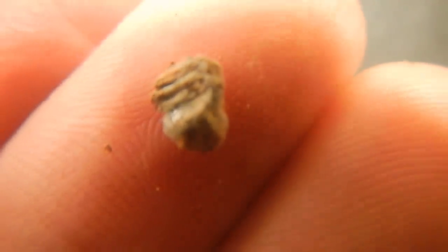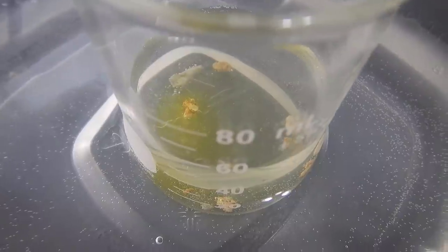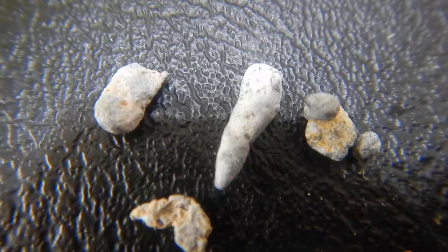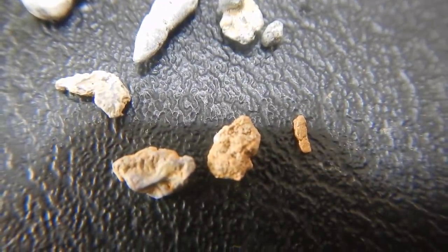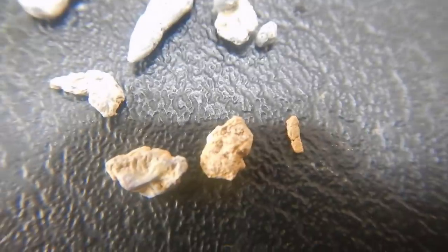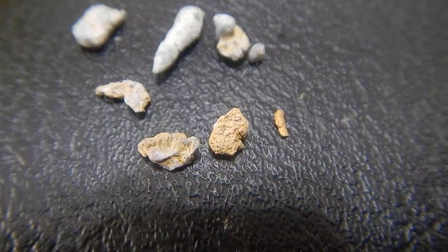That's my thoughts at the moment. And the fact that my acid is turning yellow definitely means there's an iron component to this, which again is probably lead that has iron staining its surface, making it yellow. So after dissolving in hydrochloric acid, some of these pieces are definitely just lead — that's exactly what lead looks like after a quick soak in hydrochloric. But some of them still look like sponge gold or something. That's the little piece of gold I had put in there just to serve as a test. We got these two pieces really looking like gold, and then a bunch looking like lead. The acid has turned yellow, so it's definitely dissolved iron off of that lead, and that's probably what was making the lead look yellow — some iron staining on the lead. But some of these pieces still could be gold.